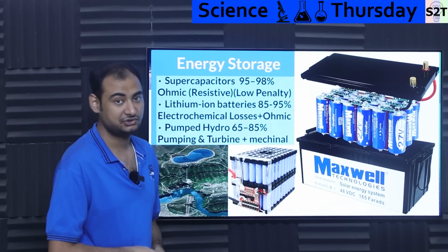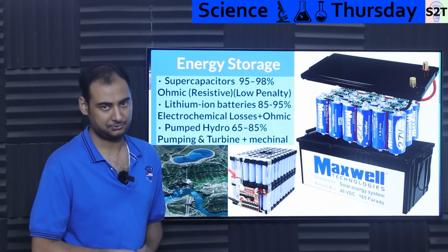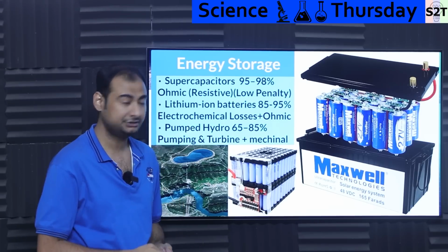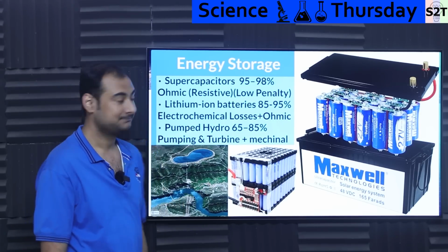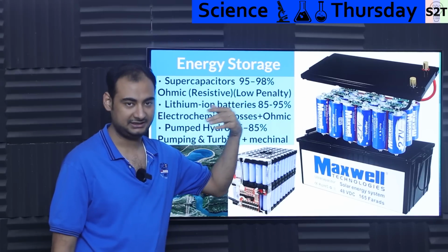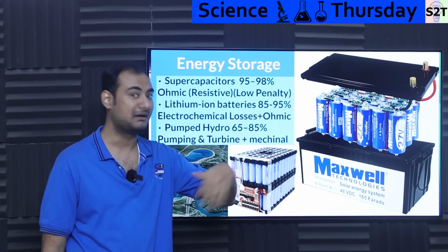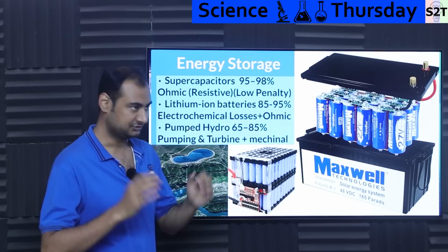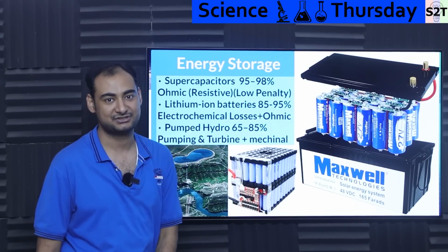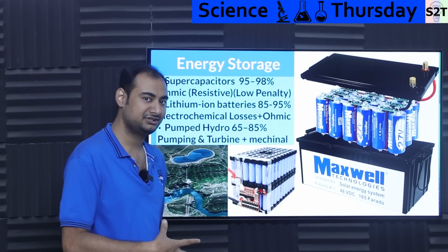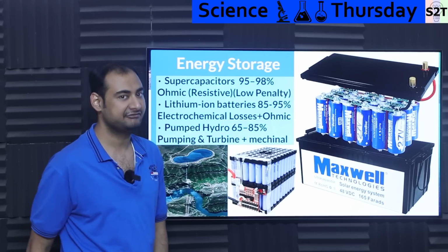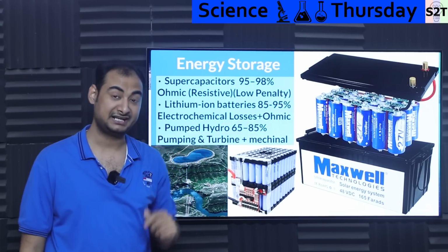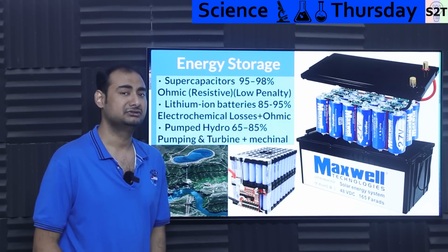Now we come to energy storage systems. So the best option you have, if you are so sensitive, like I need something good, supercapacitor is your best puppy. Basically, a basic supercapacitor that you can just buy, and again, I'm not talking about quality systems that are used for fancy things, will be almost 95% efficient. Meaning, if you dump 100 units into it, you should be able to get 95 without issue. And the top quality ones can easily dump 98 units out. So it is very efficient.